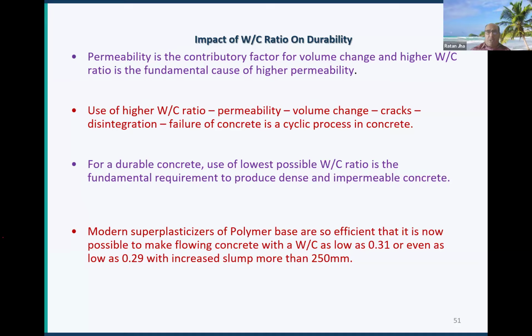structure will drastically reduce. Use of higher water cement ratio causes permeability, then volume changes, cracks develop, and disintegration of concrete. Failure of concrete is a cyclic process. With the use of higher water cement ratio, what will happen? The permeability will increase. Permeability increases, the volume changes. Volume changes, cracks will appear or disintegration. And if your concrete disintegrates, failure of concrete is bound to happen.